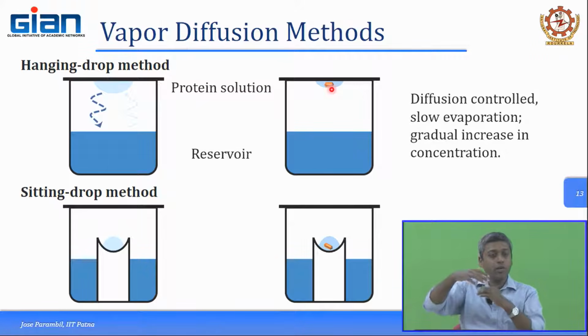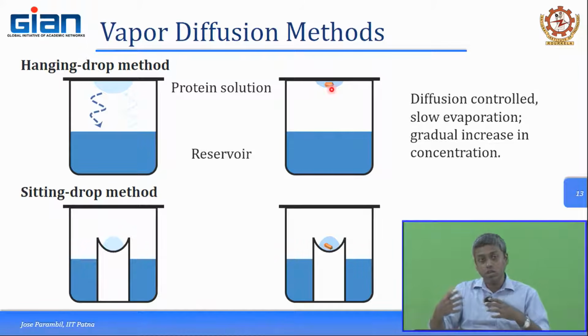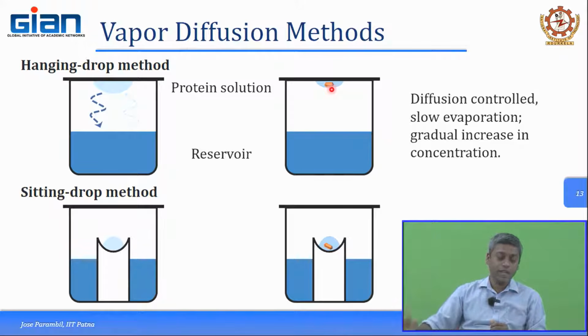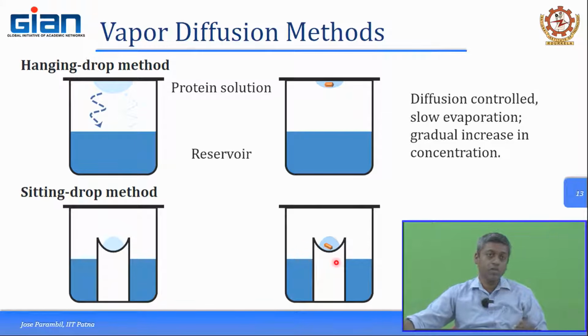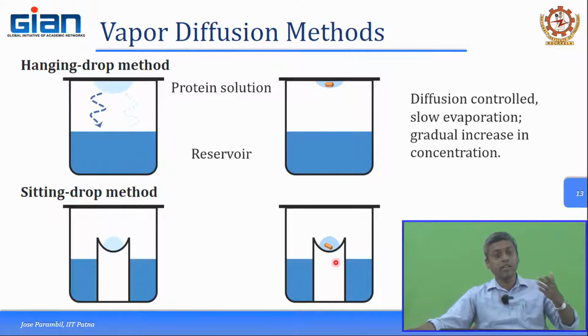So, it is more or less a uniform surrounding system in which to grow. The growth would be much more uniform in a hanging drop method, whereas in the sitting drop method, the bottom surface might be interacting with the crystal, which changes the shape and morphology and so on. So, that sometimes becomes a difficult task in order to retrieve the crystal from the sitting drop method.